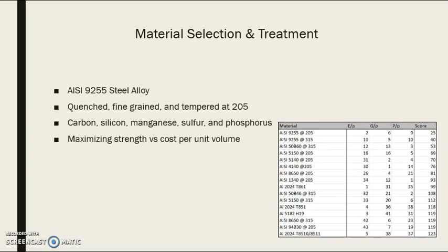These springs are initially made from cold forming, and then they go through different treatment processes to form them into the mechanical and material properties that we desire. Now, if you see on the right, those are the scores for all the materials that we have tested. AISI 9255, quenched, fine grained, and tempered at 205 degrees Celsius has the lowest score, and in our case, the lowest score means the best material.